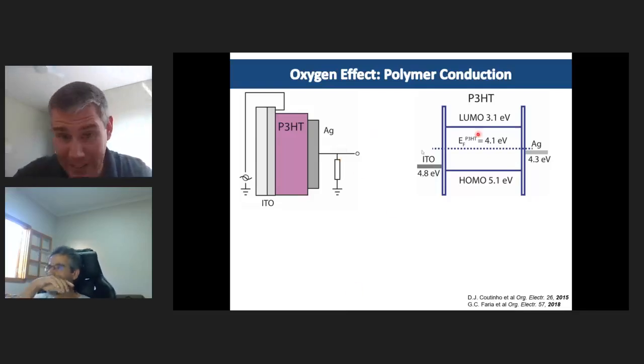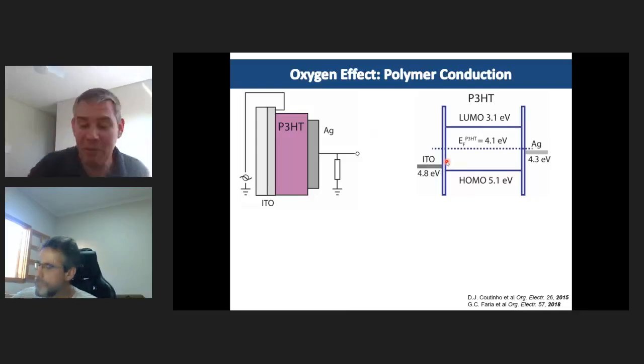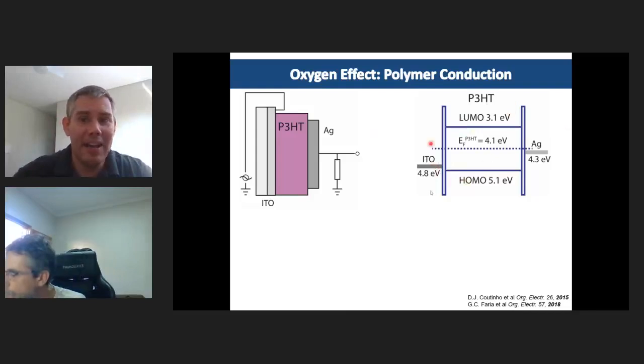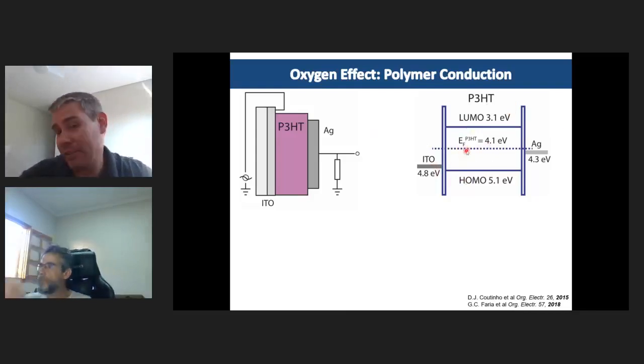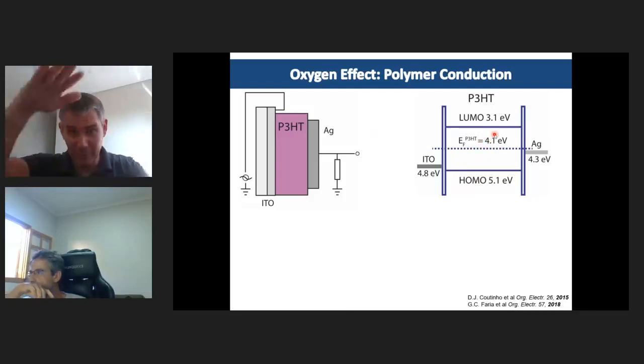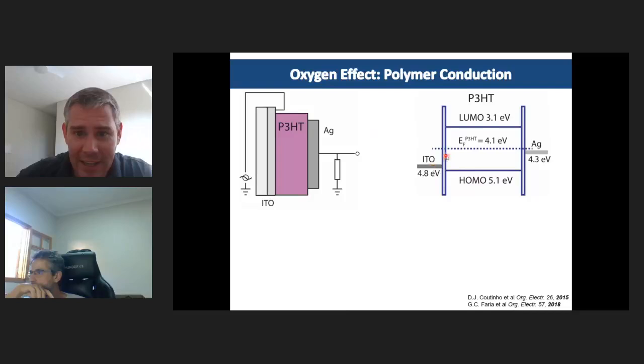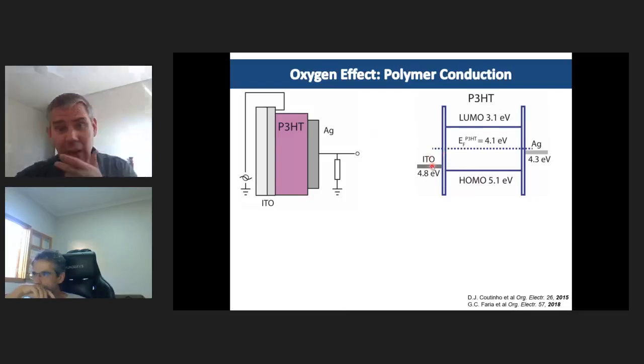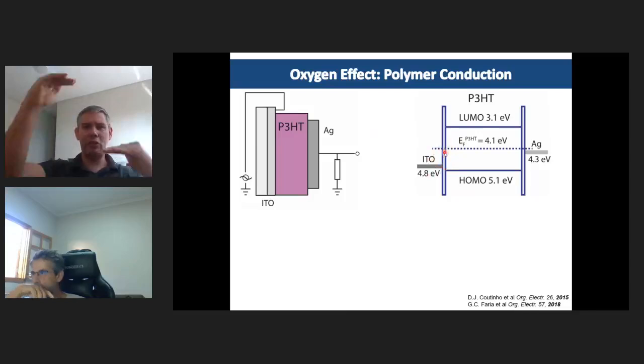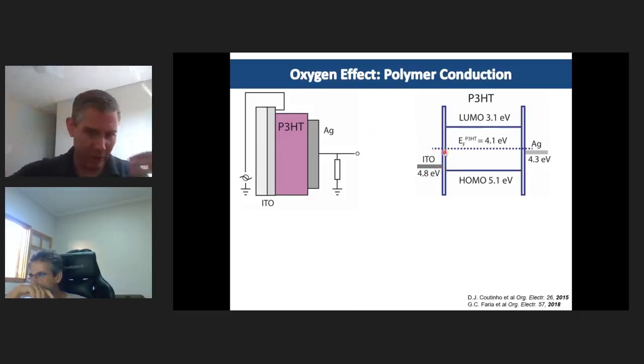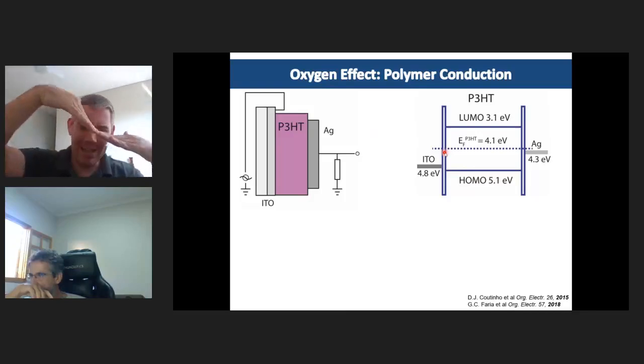So okay, we thought, let's get back to the drawing board and see what happened. And of course, we lost something. If you look at the energy diagram here, the energy level or the Fermi level of the electrons in the semiconductor is around 4.1 for a neutral material, lying in the middle of the band gap. And you see that in this interface, the work function of the ITO, which is the oxide, is actually very big, around 0.7 electron volts higher. And actually there is an equilibrium that has to be achieved, because there are such differences in energy between these two work functions or Fermi levels that in that particular interface, nature acts to sort of bend the energy to make that transition smoother.